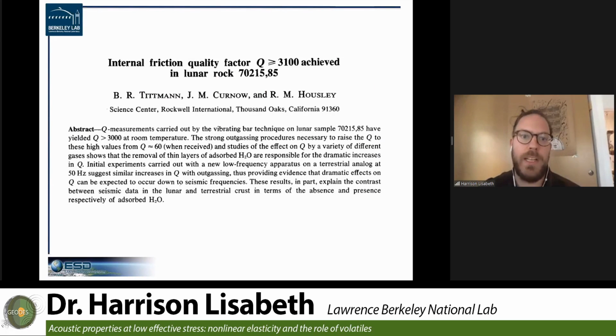Meanwhile, this guy, Bernie Tittman, was doing some interesting rock physics experiments, doing bar resonance experiments to measure the Q on some material from the moon and also various analog materials. And the materials from the moon showed terrestrial values of Q around 60 when in humidity. But when basically baked off and put in ultra high vacuum in order to drive off trace amounts of water, he was able to recover values of Q similar to those actually measured on the moon, up to 3,000, suggesting that thin layers of adsorbed water were responsible for this dramatic decrease in Q when materials are found in ambient humidity.